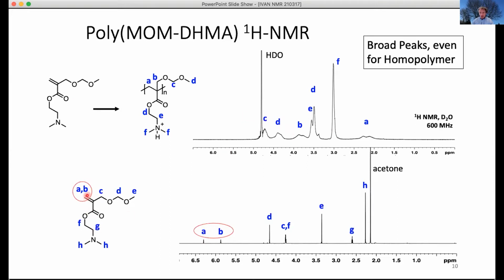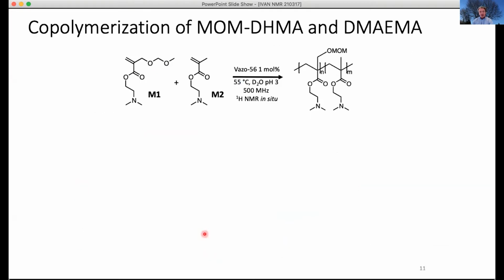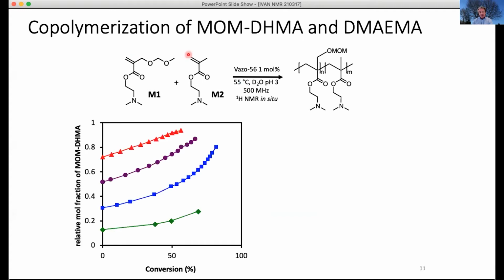But the monomer, of course, has beautifully sharp signals, and in particular the vinyl groups, which are very small here, but believe me, they are sharp and easy to quantify. So tracking relative consumption of the two vinyls allows us to track the shift in composition of the polymer over time as it's formed.